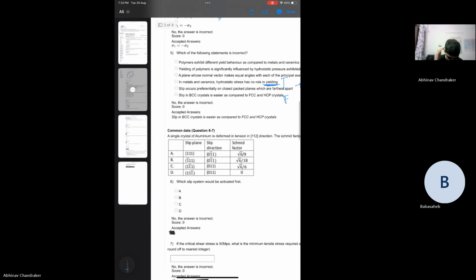A single crystal of aluminium is deformed in tension in the 112 direction. Schmid factor is given below for different slip systems. Which slip system will be activated first? So for the same family of slip systems, we have been given different Schmid factor values. It is the 111 slip plane and 110 slip direction family. We have been asked which will activate first.